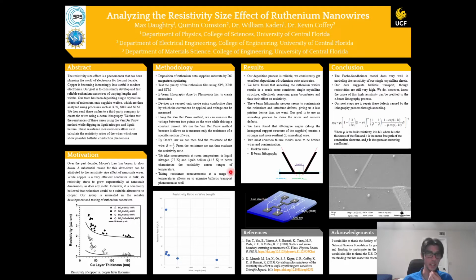So when we take these measurements, we take one in liquid nitrogen and one in liquid helium, as well as a room temperature measurement. And when we do this, we can calculate the resistivity ratio of higher temperature to lower temperature, which of course, higher and lower are very relative. This resistivity ratio allows us to detect ballistic transport. Ballistic transport is where the mean free path of the electron becomes larger than the length of the wire itself. And the mean free path of an electron is basically how far it can travel without a collision.